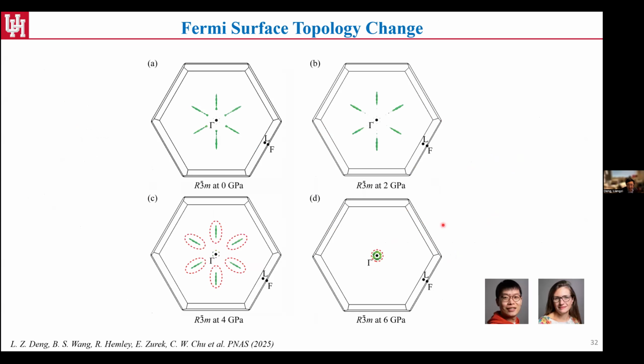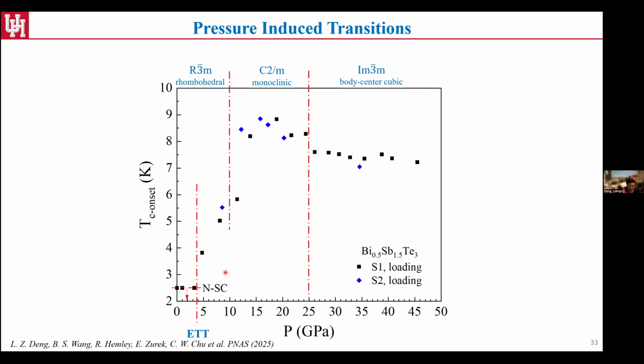And then Eva and her postdoc, Busen, at that time, also joined to study this material and really look at the Fermi surface topology. And then he mapped it out with the same structure at 0 GPa, 2 GPa, 4 GPa, and 6 GPa. Eventually, we can see a very clear difference between the 4 GPa and the 6 GPa. So that further supports the idea that there's a Fermi surface topology change in this range that really makes the superconductivity emerge, or kick in. So that's very beautifully explained. Now we can really assign these 3 critical pressures to 1 electronic topological transition and 2 structural transitions, right?